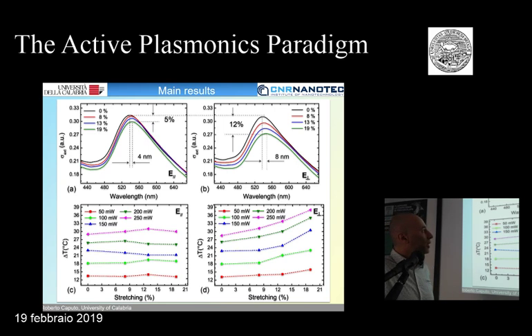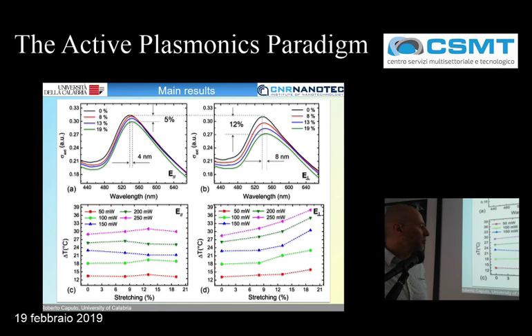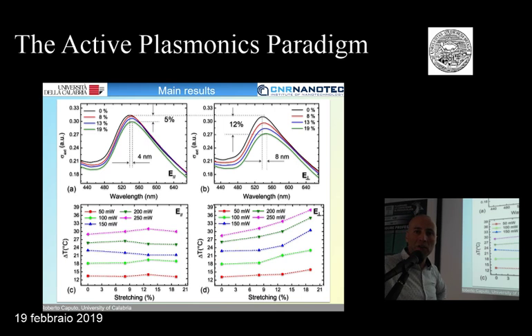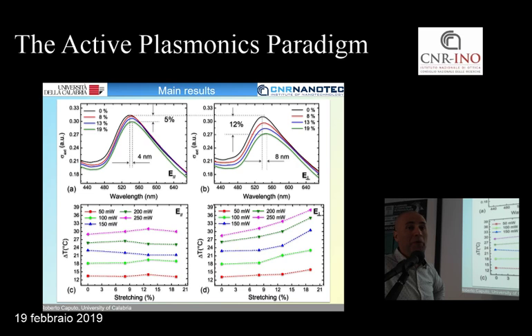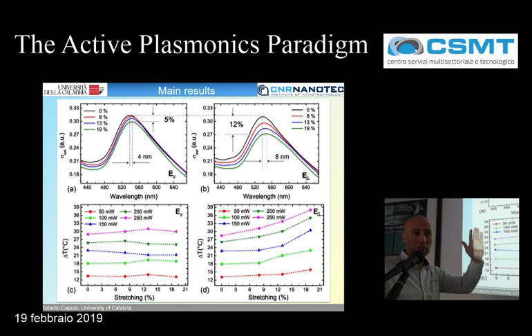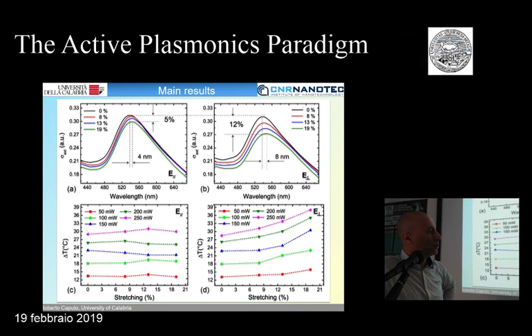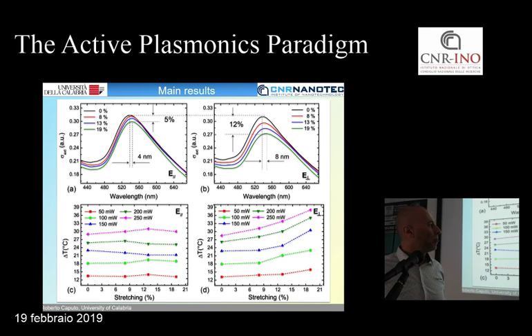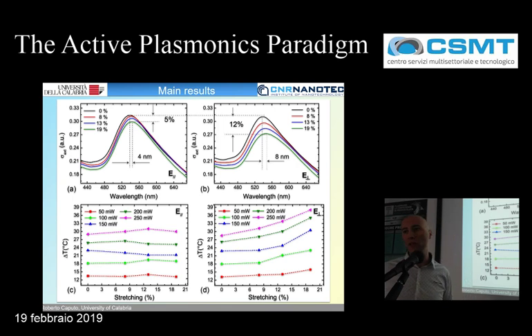And in particular, if you use a pumping excitation which is parallel to the stretching direction, nothing really happens. So you can change the intensity of pumping, but by stretching, in principle, you keep the same, a constant temperature. There is no change of temperature by stretching if you use pumping polarization along the stretching direction. The situation is much different when instead you use a polarization which is perpendicular to the stretching. If you remember, with the polarization perpendicular to the stretching, we had the very efficient resonance shift. This resonance shift, in principle, corresponds to a change of temperature, a fine control of the temperature of the sample. So in this case, for example, you can change by just stretching from 29 to about 40 degrees. So you have a range of change which is quite useful.